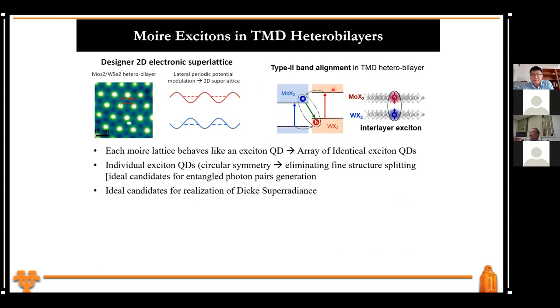Now you have this type 2 alignment. So the band gap that I described is really for the electron in the MoS2 and the hole in the WSe2. So this will be the interlayer exciton. This is a band structure. And then if you take this quasi-particle band structure and subtract the exciton binding energy, that will be your interlayer exciton transition energy.